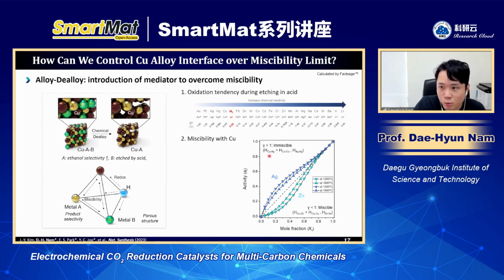What we did is we used the FactSage thermochemical program, and when you calculate the activity coefficient according to the type of metal, we can get this kind of curve. In the case of silver, because the slope is larger than one, the activity coefficient is larger than one. So in this way, we categorize it as an immiscible one. And in the case of zinc, the activity coefficient is lower than one. It means that it is very miscible with copper.